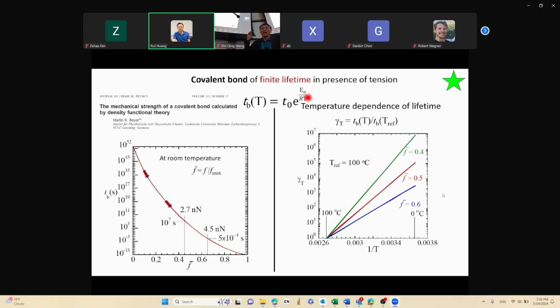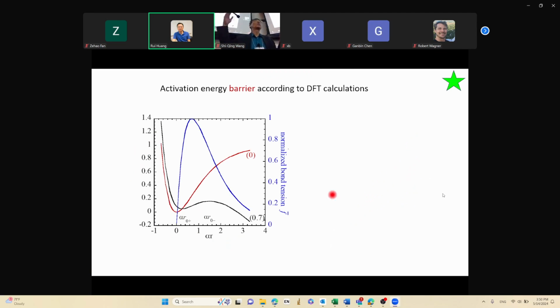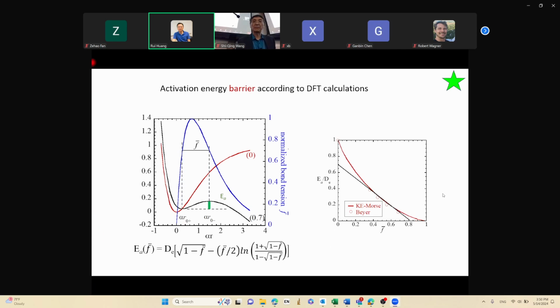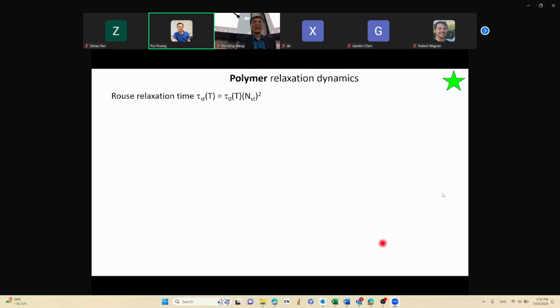In any case, you can do density functional calculation and show that as I load the bond with more and more tension, the lifetime of the bond crashes down, okay? Crashes down. And at different temperatures, at a given level of tension, the bond lifetime is longer and longer if it's colder and colder. So you can go through the whole nine yards about how to relate this bond tension to lowering the barrier. I'm just going to skip it because it's so boring. But it's known since the 1940s. The density functional calculation, of course, was more recent, in 2000.